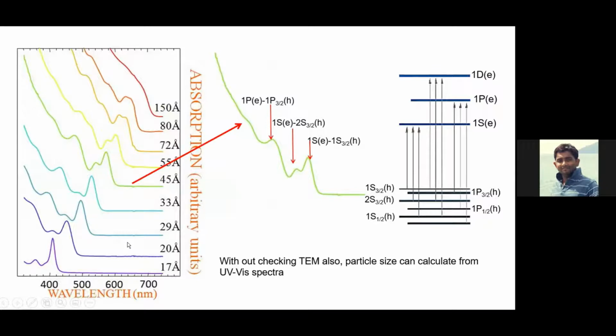Because when you go from blue to red, you can see it's tuning from the blue part of the spectrum to the red part of the spectrum, and it can absorb the whole visible window. And these are the different sizes of the nanocrystals, from 1.7 nanometers to almost 15 nanometers. And these are all from the same nanoparticles.